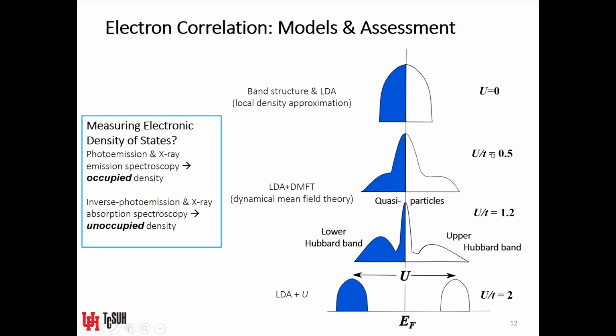Adding some electron correlation will then alter the density of states, okay, such that you get the development of what's known as high energy spectral weight. And high energy meaning at energies higher than the Fermi energy, okay? So you get these shoulders in the spectral features. Okay, and so I think you can see it, but let me minimize. Okay, yes. So if the Coulomb energy becomes equivalent or on par with the kinetic energy term, then you start seeing the formation of what we call upper and lower Hubbard bands, okay? And then in the case of very, very strong insulators, if you will, then you can find something.